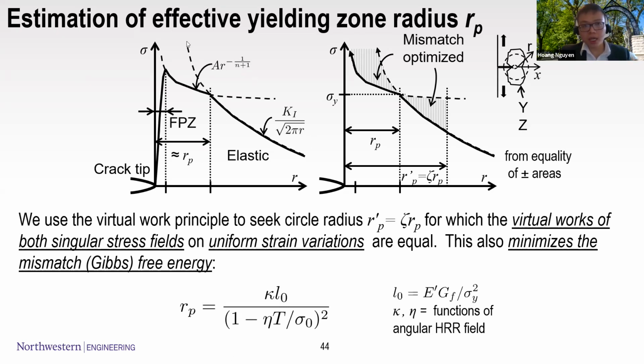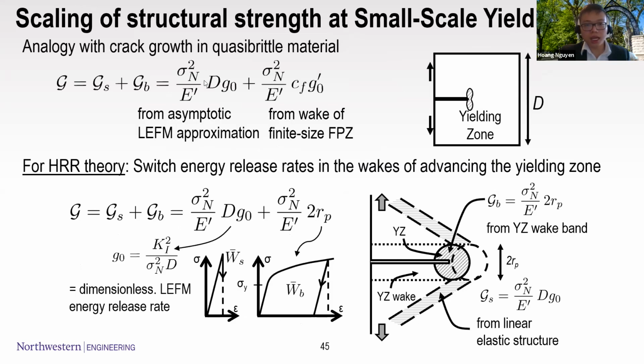So basically, we can use the virtual work of the singular stress field and uniform strain variations. We can come up with the calculation for such an R_p, and then we just use the same strategy, which is breaking the energy into the terms that depend on size and the terms that don't depend on size here to scale the materials. However, the caveat of that assumption is that we should always use it for the scaling of structures that completely contain the yielding zone.